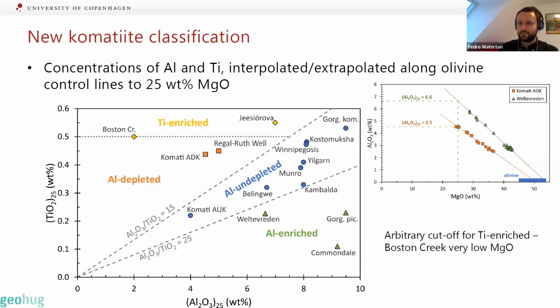So in this paper, Nick and I came up with this new komatiite classification, and we wanted it to be pretty simple and quite close to what previous classifications have used. So the idea here is that you just plot up your komatiite data along an olivine control line, aluminium and titanium against magnesium, and then you just interpolate or extrapolate to 25 weight percent MgO. Why 25 weight percent? Well, this is kind of where a mode in komatiite compositions lies.